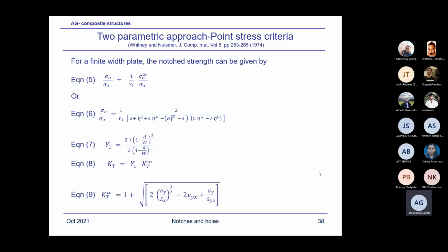Yes, sir. And I'll be talking about it next week, about the damage tolerance and durability approach, which would be very useful. But sir, delamination growth is also a kind of propagation, just as in metal, sir. Delamination, it is propagation in composites like a crack in metal, which people have tried to correlate using da/dN as a function of a stress intensity factor or strain energy release rate, similar to metal. Yes, sir. However, my experience has been that in composites, the delamination jump occurs quite often under load. Suddenly the crack jumps, and that phenomenon changes the behavior. In metals, the crack doesn't jump. It always grows slowly.